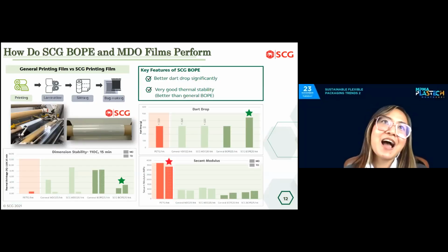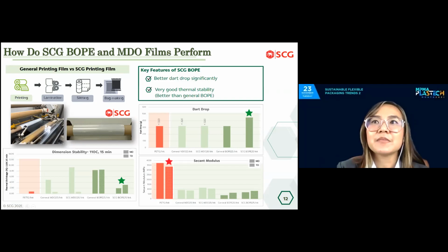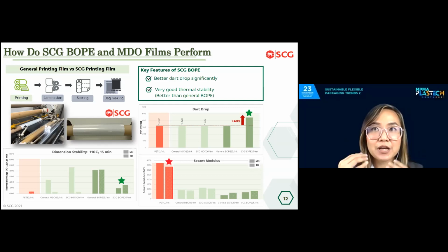So the next question is, how do SCG BOPE and MDO film perform? So let's see how it's different. To compare with the conventional printing layer, in this case, I would like to compare with the PET. And you can see here, SCG BOPE is good not only for recyclability, but also the dart drop property. SCG BOPE can show 40% higher dart drop compared to the conventional printing layer and general BOPE and MDO solution. However, SCG BOPE cannot fulfill all the properties of the PET, especially the film stiffness, as you can see in the secant modulus.